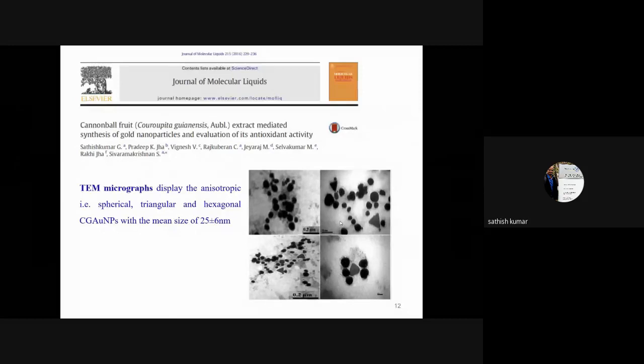So in another study, we explored the fruit extract. This time we have explored the fruit extract of the plant Couroupita guianensis, and this time we have synthesized gold nanoparticles. And here you can see the gold nanoparticles with a mixed shape and size. It has both triangle and spherical sized particles with the size range of 25 plus or minus 6 nanometer. So here also we cannot say this is mono-dispersed particles.